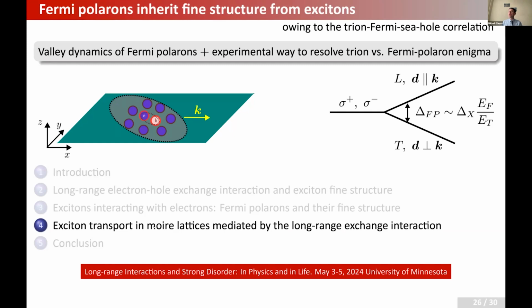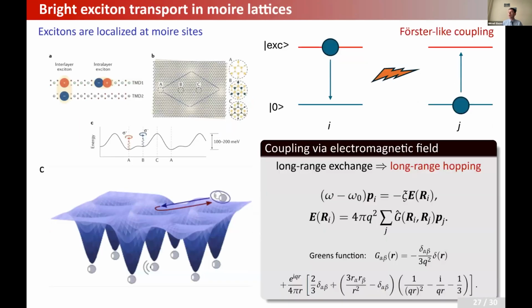I want to speak a little bit about exciton transport in moiré lattices, which is mediated by the long-range exchange interaction between electron and hole. So the physics is very simple. We have again heard a lot about moiré physics, and basically if you put one TMD layer on top of the other, then